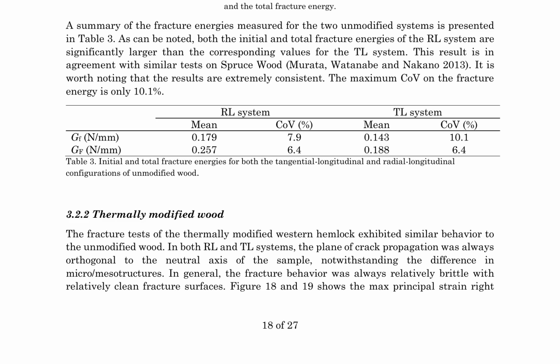The RL system had a mean initial fracture energy, GF, of 0.179 N per millimeter and a mean total fracture energy, GF, of 0.257 N per millimeter, with COVs of 7.9% and 6.4%, respectively. In contrast, the TL system had a mean initial fracture energy, GF, of 0.143 N per millimeter and a mean total fracture energy, GF, of 0.188 N per millimeter, with COVs of 10.1% and 6.4%, respectively.